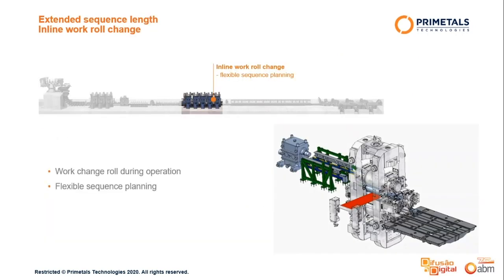this is not the case, as we can see here on the example of the inline work roll change. The inline work roll change allows to open the work rolls during rolling and to execute the roll change like well known from cold rolling. During the operation, the final thickness is increased as the changing stand is dummied. After roll exchange, the plant goes back to desired minimum thickness and the sequence length is doubled.